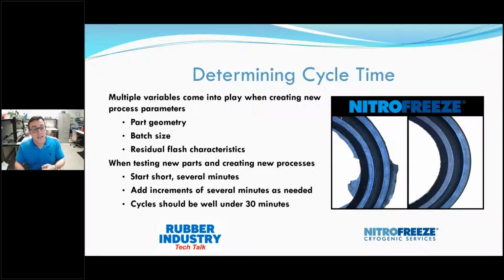Okay, the flash is getting removed, but there's still residual flash. Put the parts back in, run them for another couple minutes, take them out. Maybe at this point, you have achieved what you're looking for. You might need a little bit more time. But at the end of the day, whether it be cryogenic deflashing with the media blasting or cryogenic deflashing with the tumbling, your cycle should be well under 30 minutes.